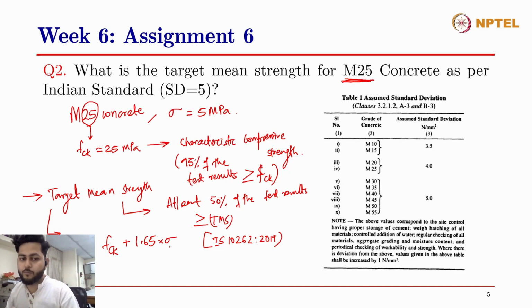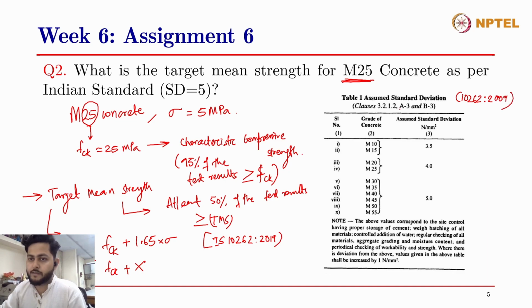2019, it has been modified, and there are two ways of calculating this. One is by the standard deviation sigma, which I mentioned, and the other is by FCK plus X. X is a factor which takes into account both the standard deviation and the 1.65 factor as well. So I have taken this table from 10262 2009, and here is the assumed standard deviation for different grades of concrete.